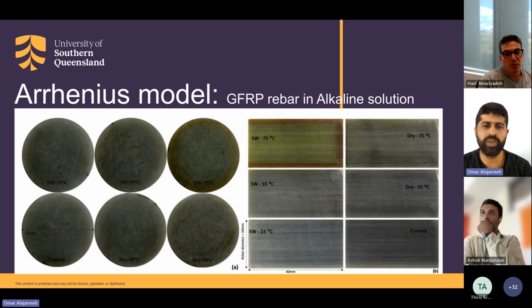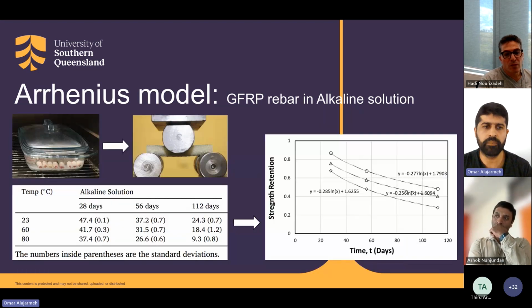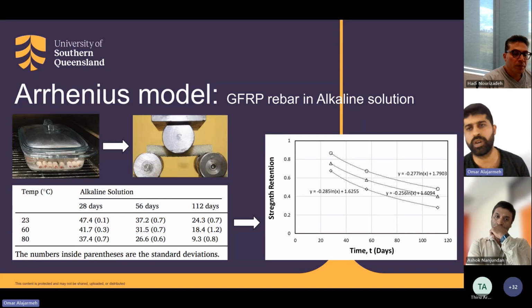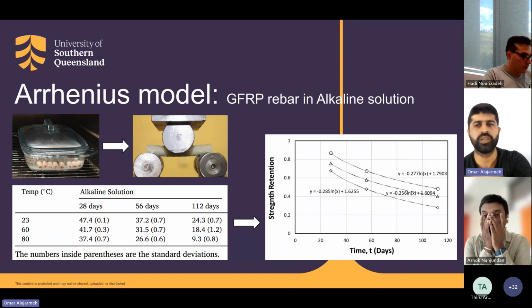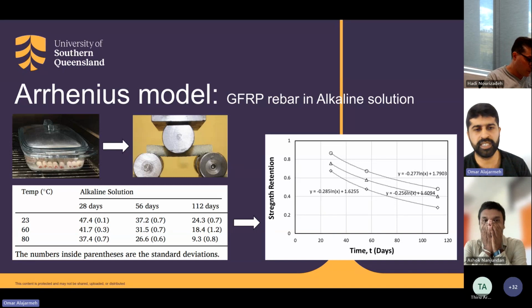So for GFRP, what we have done previously is we took a reinforcing GFRP bar and cut it into small lengths. The target for us was to test it under the interlaminar shear test, which is a 3-point bending. We put that bar in alkaline solution for different durations and different temperatures: 28 days, 56 days, and 112 days, at room temperature, 23, at 60 degrees, and at 80 degrees. And we started testing those bars after these points.